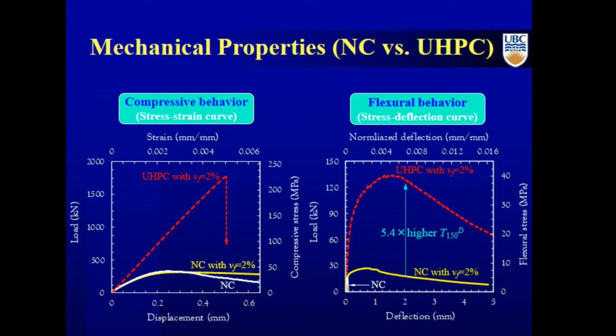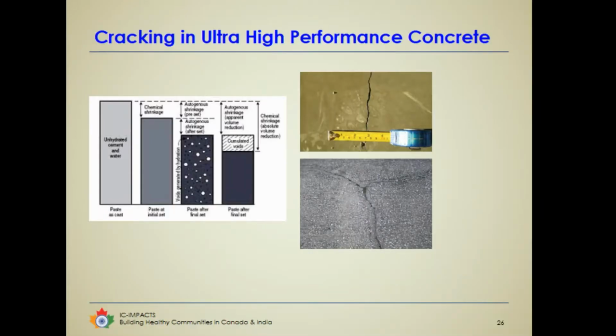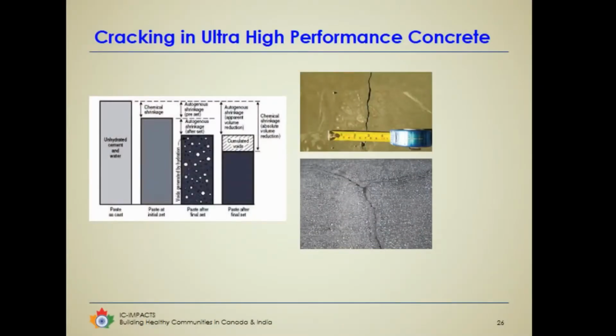So a number of these applications have come about using ultra-high performance concrete. One of the problems with this material is it also has very high autogenous shrinkage. Now, concrete shrinks, as you know, and these ultra-high performance materials, which have very low water-cement ratio, end up having very high probability of cracking, which is either what we call chemical-induced shrinkage or autogenous shrinkage.